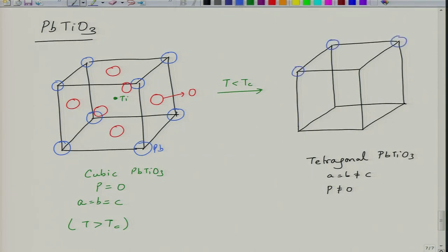So in this case what will happen is that you have similar atoms sitting at various positions. This is oxygen, don't worry about the sizes, and this will be titanium. Now the titanium in this case will be slightly off centered. So this is the central position. So titanium will either be here or it will be here. So this is the downward or upward movement of titanium. So you can see that oxygen here makes an octahedra. This is oxygen octahedra, right?